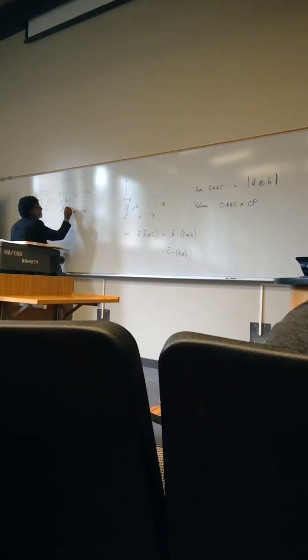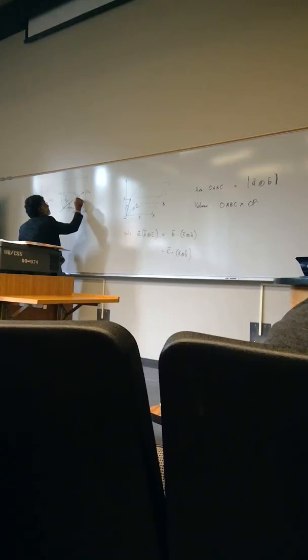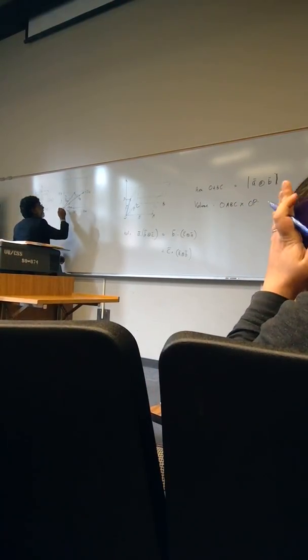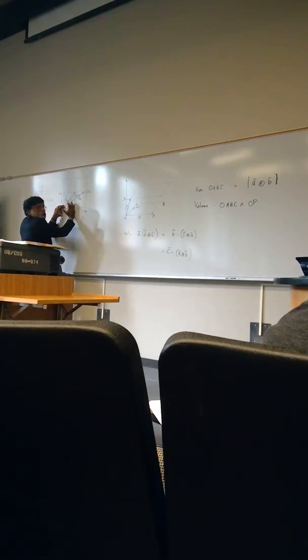So this vector is the 1, 1, 0, the reciprocal lattice vector. This vector is the G1, 0, 0. And so on. And this would be the vector G2, 1, 0. These are the reciprocal lattice vectors. And the planes are perpendicular to this. The spacings of these planes are given by the length of the reciprocal lattice vectors.